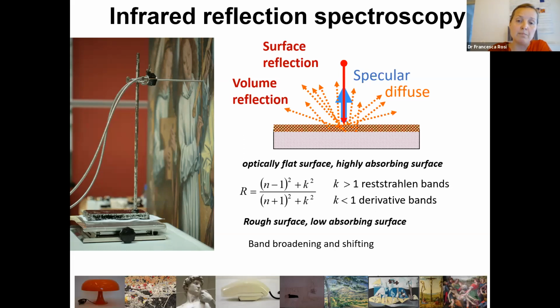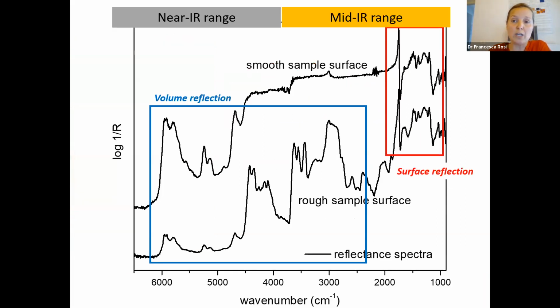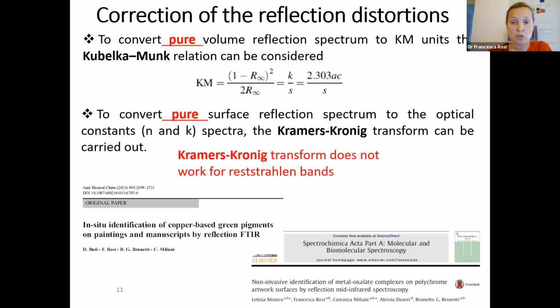When we work with organic binders, organic material in general, we have surface reflection spectra with mostly derivative-like bands. The situation is quite complicated because we still have information about the chemical composition of the material, but it is modulated according to the optical properties and the two contributions. The surface reflection dominates in the fingerprint region when we have strong absorption, whilst in correspondence of lower absorption bands or in the near infrared region, the volume reflection dominates the spectral features, with the enhancement of minor combination and overtone bands, which are not distorted.